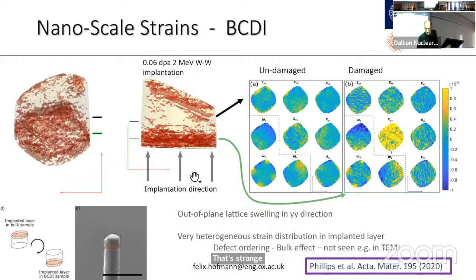One other thing I should say is that what I've shown here is just the isosurface of the strain component in this direction. The implanted layer is down here, and if you squint, can you see that down here there's a very shallow layer that looks clear? That's your surface effect. That is the effect of the surface swallowing your defects.